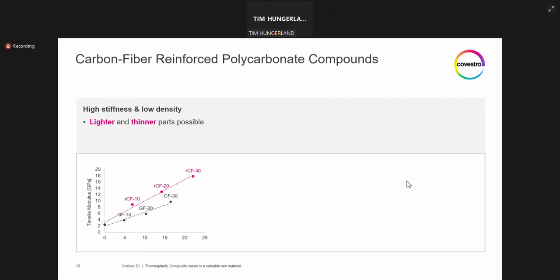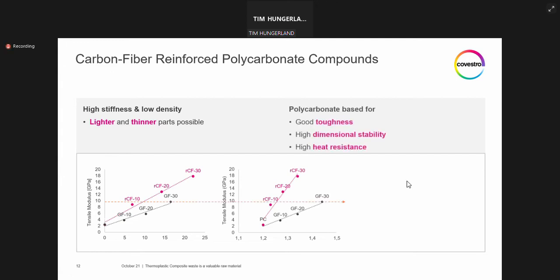As a consequence, since more glass fibers are required to reach a high stiffness, the flowability and processability of these materials can become a challenge. This then translates into limits of, for example, achievable wall thickness and part design when comparing glass and carbon fiber reinforcements. When also taking the density difference of both fibers into account, as shown in the second graph, carbon fiber compounds offer a significant weight-saving potential, which increases with higher stiffness requirements, as shown on the right side.